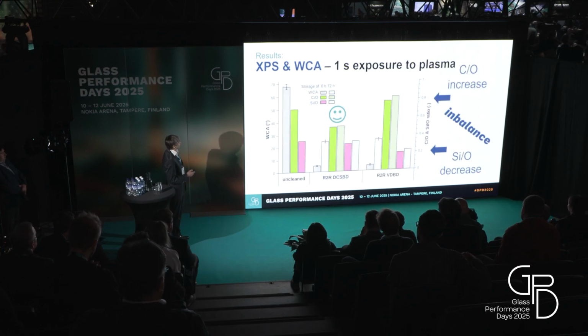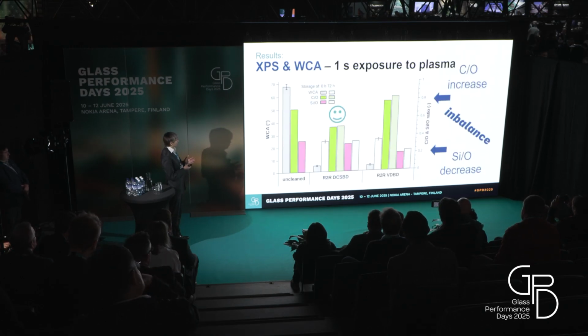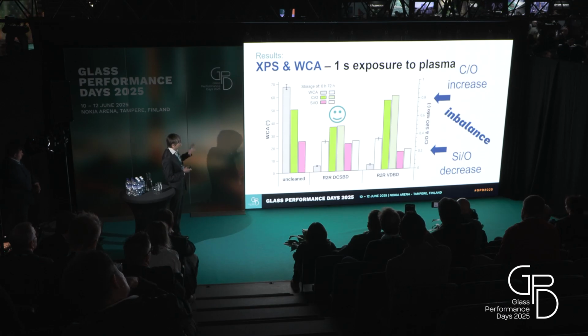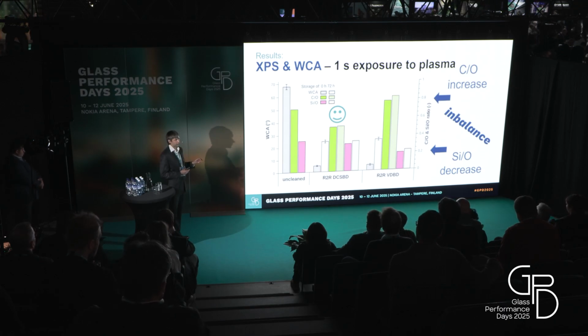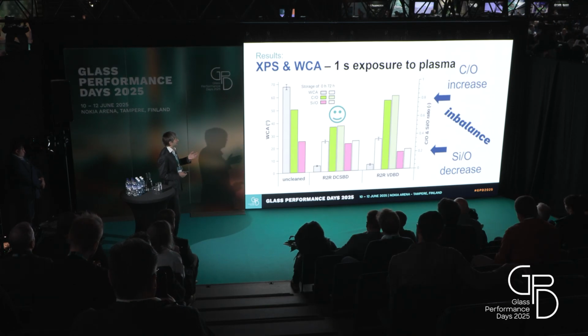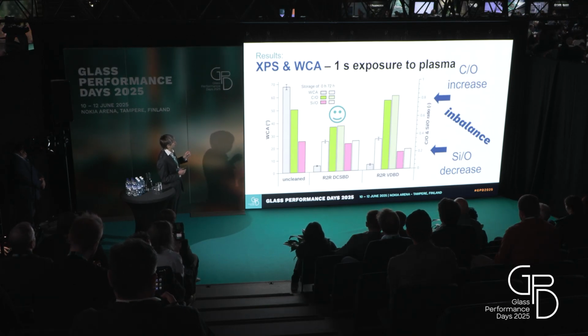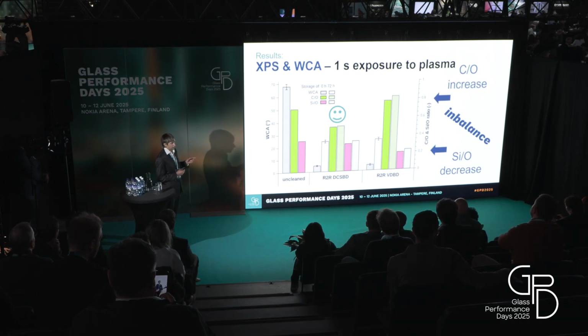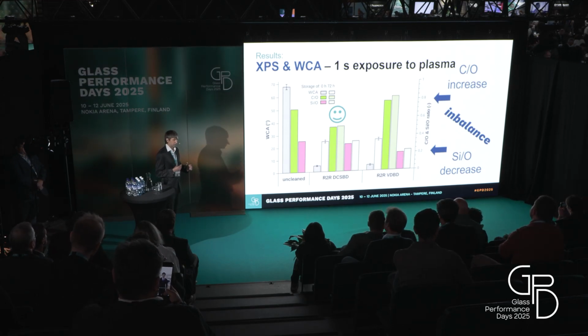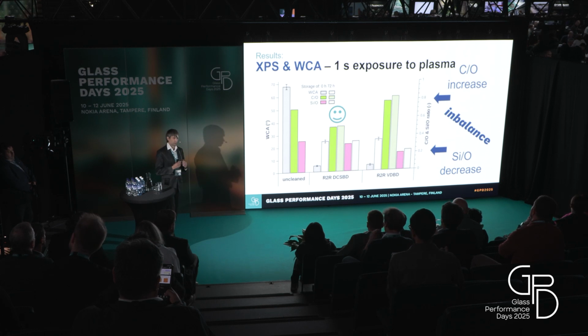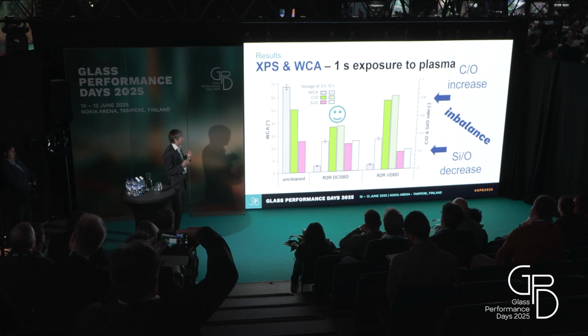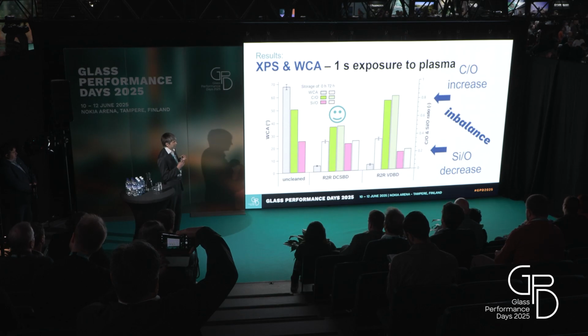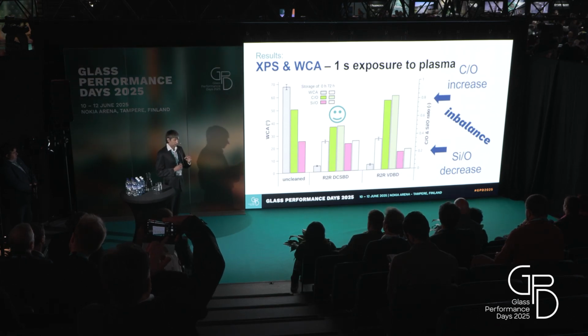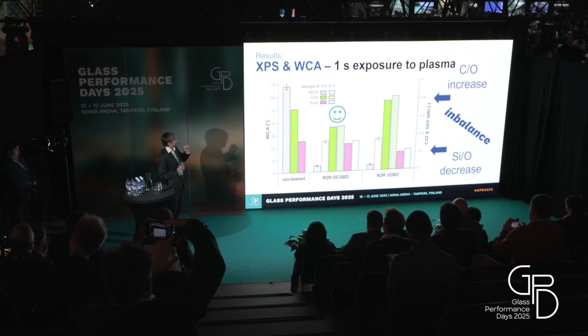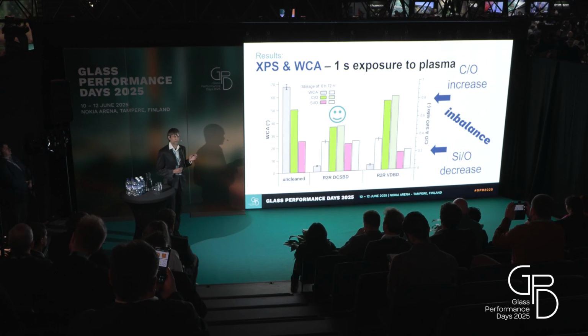And to see the graph, when we compared the water contact angle, which very significantly decreased after the 1 second exposure, and the change in the ratios of carbon and oxygen and silicon and oxygen can help us to understand how the content on the surface is changed. Because if you lose the Si/O ratio, it means that you stop detecting part of the silicon, because the analytical depth of XPS for glass is only 3 nanometers.